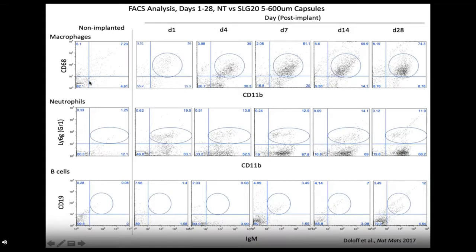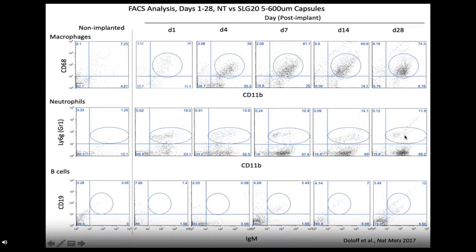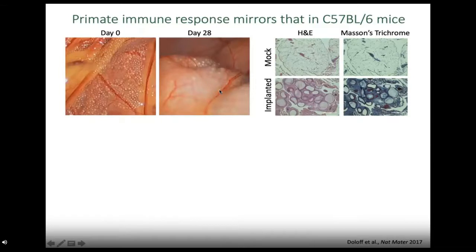The dissociation technique removes 95-99% of the cells; you can see the capsules are intact but most of the immunologic response has been recovered off the surface. We stained with different antibodies — in the top case, CD11b and CD68 for macrophage response. You can see day one, day four, day seven, day 14, day 28 increasing over time — macrophages were the largest dynamic responder. Neutrophils increased at day one then plateaued and decreased slightly as macrophages compositionally took over. B cells showed up more prominently in a delayed fashion at day seven.